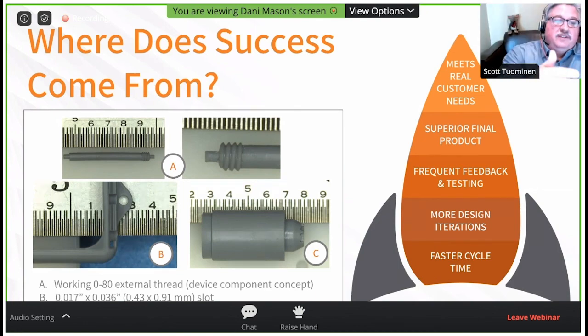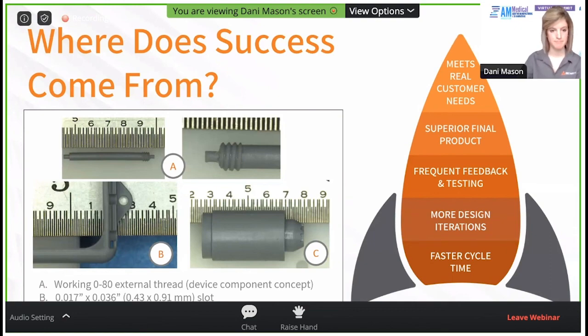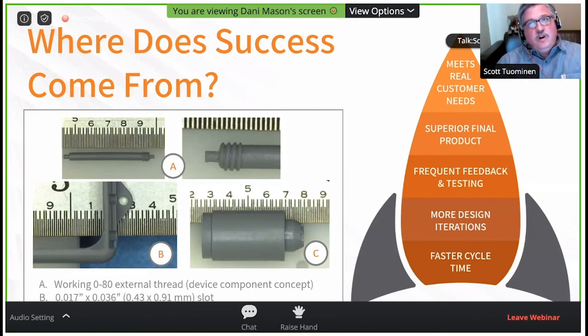That's why being able to minimize the amount of support helps reduce the amount of art that needs to be applied after the print job has been done. There have been a lot of tricks too with learning how to cure, not necessarily with your technology, but other SLA technologies. You get part warpage. Learning when to anticipate that, how to constrain your parts if they do warp, how to then reflatten them. We've learned very quickly what the heat deflection temp of all of our materials is in our lab. We know exactly, right from memory, because we've melted enough parts and deformed enough parts to have learned that the hard way.